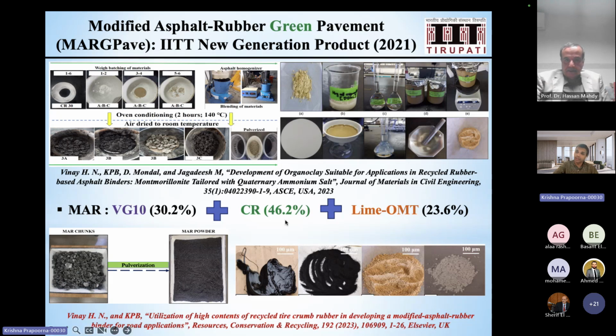We even went to about 46%. In fact, recently, one of the papers that we published has about 60% rubber. So you can go until about 60% rubber now instead of just 20%. That means you are now getting into the circular economy concept. Okay, so we have this as the ingredient that gets charged.